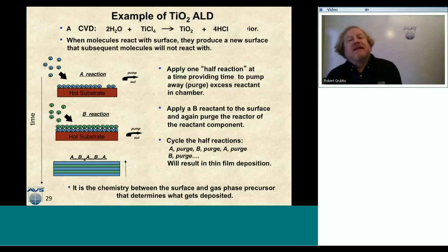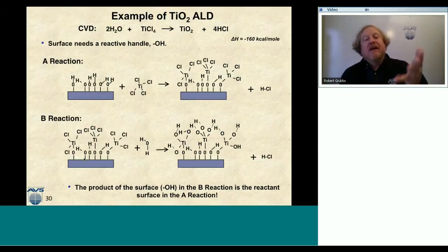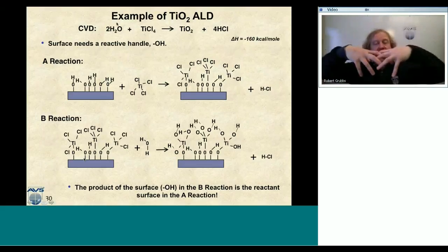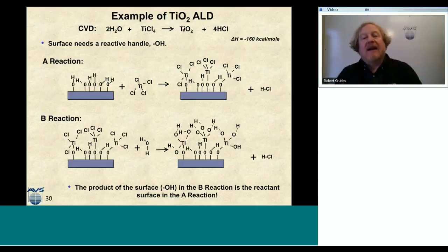So here's the example of titanium oxide ALD. We take titanium tetrachloride and water, and we bring them into a chamber, and we react them simultaneously in CVD, and I make titanium dioxide and I make hydrochloric acid. So this reaction is downhill. The delta H is pretty negative. And so this is the cartoon of how this actually takes place.